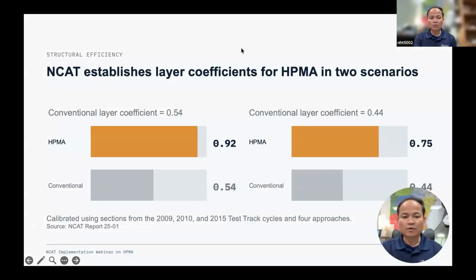So fast forward to 2024, 2025, we went back to all the data for the test track experiment. And one of the questions is, based on the test track study, can we determine what would be the structural layer coefficient for HPMA mix? And then the analysis came out that yes, you can see here that the structural layer coefficient of the HPMA layer is almost double the typical value that has been used in pavement design.